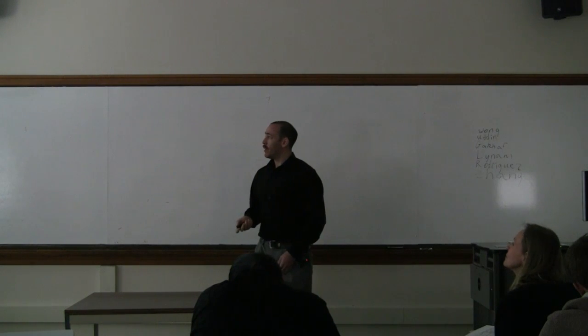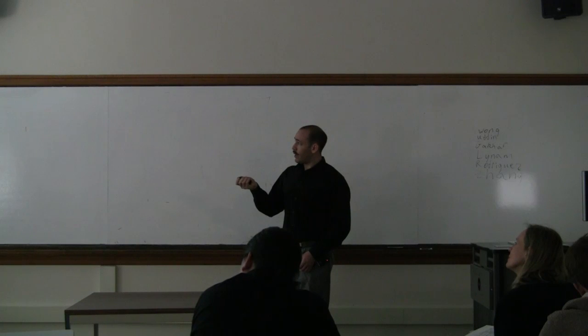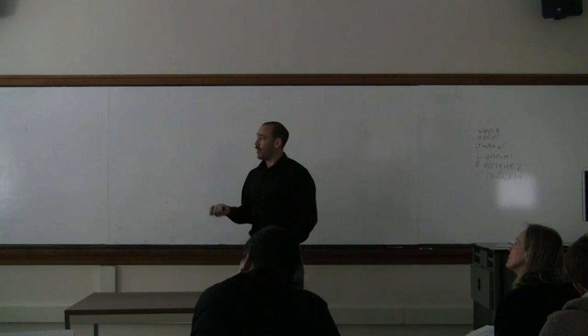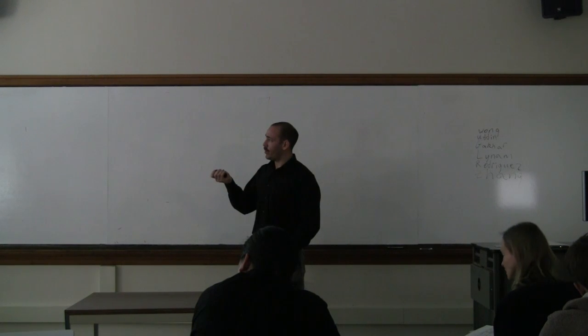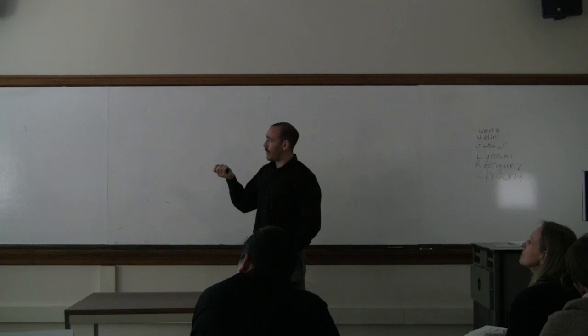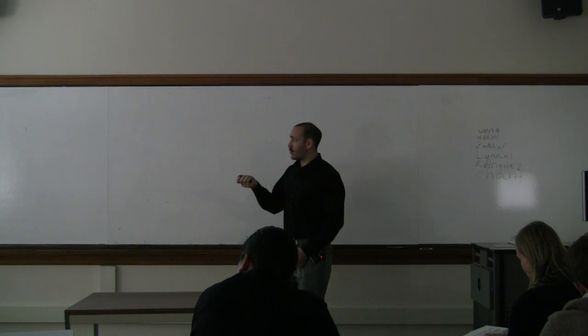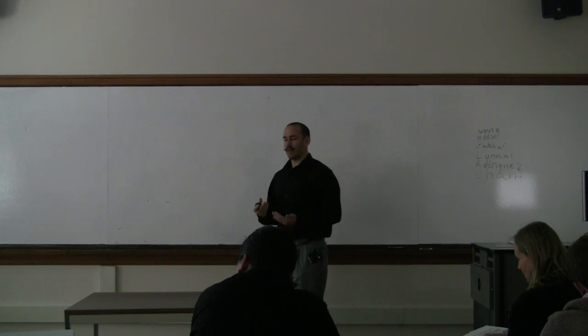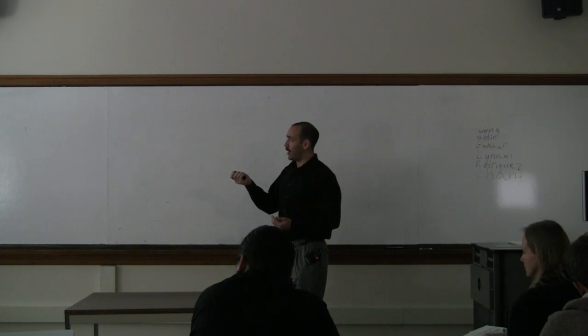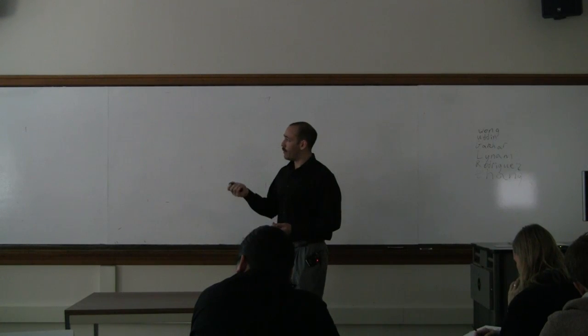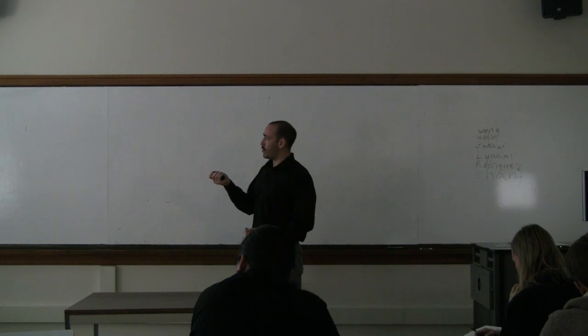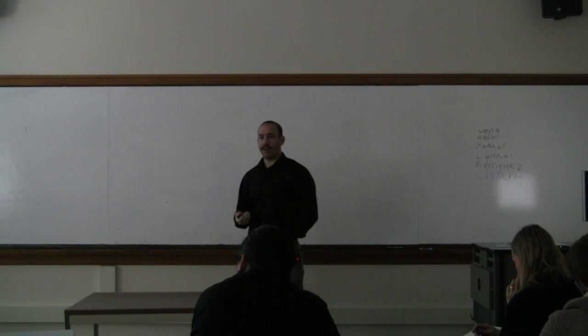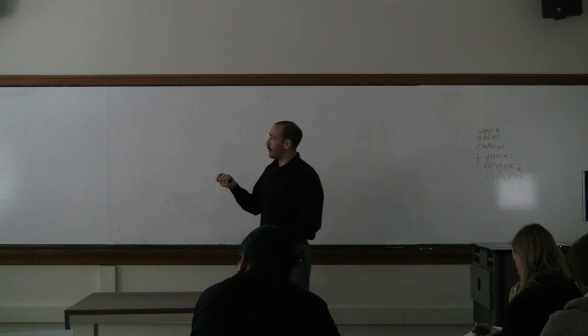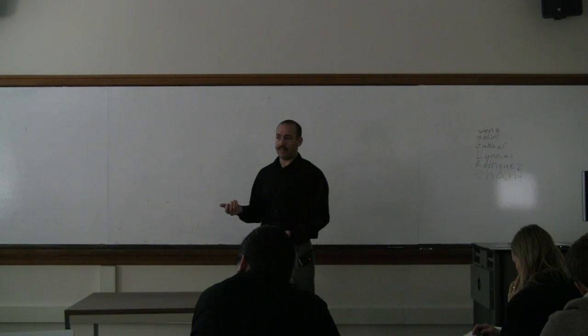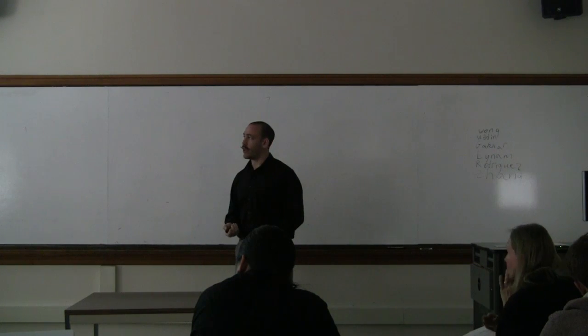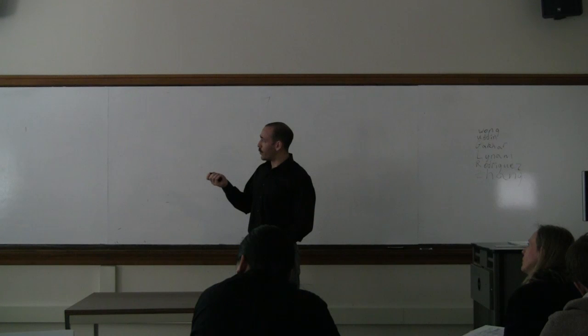we have different bonding modes that would be seen in just a typical salt. Now here we have the base aluminum alloy, we have FTIR spectroscopy results, and on the bottom we have the polished uncoated sample, the sodium molybdate salt, and on the top we have the coated sample. Now from these two graphs we can interpret where we have certain peaks on this curve, which we have blown up right here. We have some that are attributed to aluminum oxide, and we could tell this from the polished sample. And then we have water, and this is seen in our FTIR spectra because we have a hydrated coating. And then these peaks over here are for the molybdenum oxide.